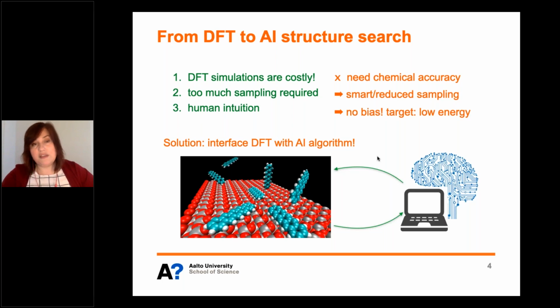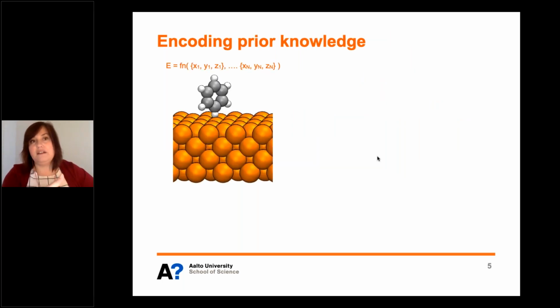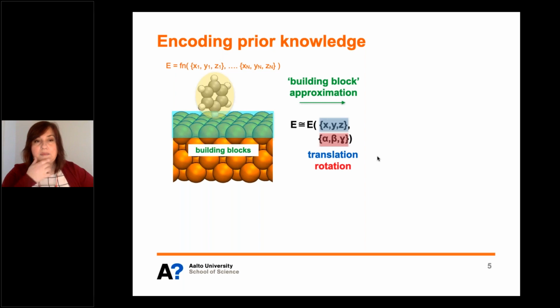And there is one thing that we can do. We can encode some prior knowledge about the chemistry of these systems. So we know, for example, that in an adsorption scenario, the structure is unlikely to deform very much. And the same for the molecule, it's not going to disintegrate. So to first approximation, we can keep these structures fixed, and we call this the building block approximation. And now an adsorption problem just becomes a function of the translation or the position of the molecule above the surface and its orientation around the surface.